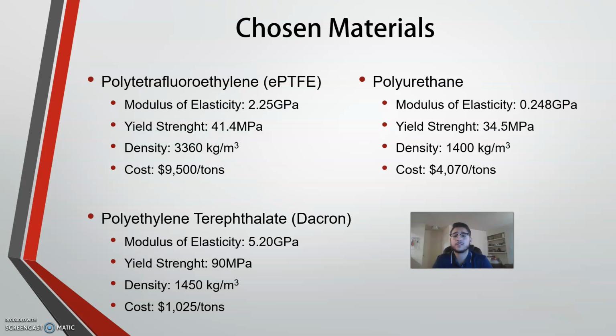Dacron has a modulus of elasticity of 5.2 gigapascals, a yield strength of 90 megapascals, and a density of 1,450 kilograms per meter cube. The cost to manufacture this material is $1,025 per metric ton. And lastly, polyurethane has a modulus of elasticity of 0.248 gigapascals, a yield strength of 34.5 megapascals, a density of 1,400 kilograms per meter cube, and a cost of $4,070 per metric ton.